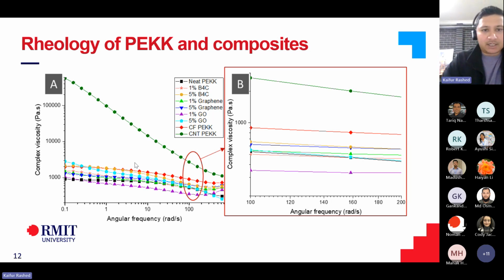So if you can see the neat PEKK, which is the black square boxes, and then graphene oxide, which goes below the neat PEKK. So graphene oxide essentially lubricated the polymer chains, and that's not something I expected, because in literature, when other people use graphene oxide, they had good success, but for PEKK, graphene oxide reinforced PEKK became extremely challenging to work with. So they lubricated the polymer chains, and then when I tried to print them, it's as if you're using an ink pen, and it's spreading too much ink, so you don't have any control over where the polymer is going. So when you design something, it's not going to be accurate when it's printed.